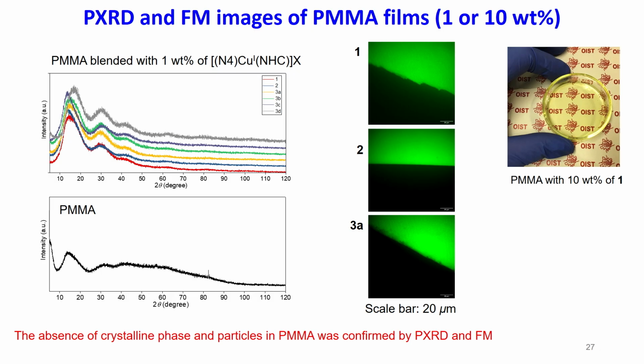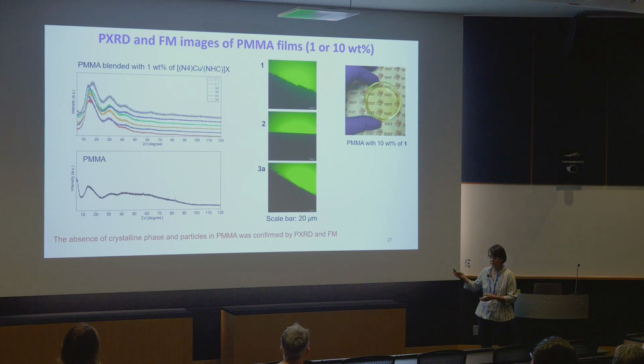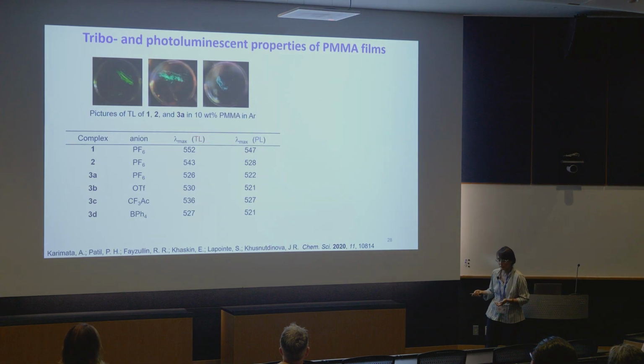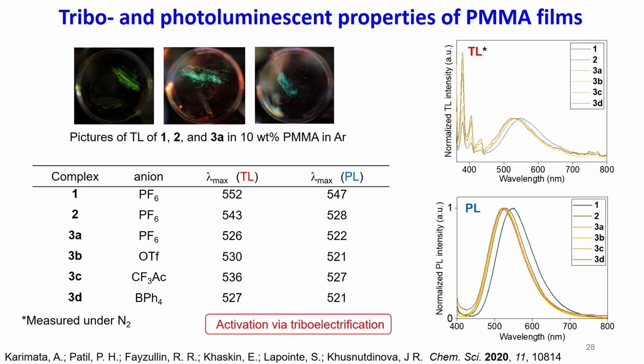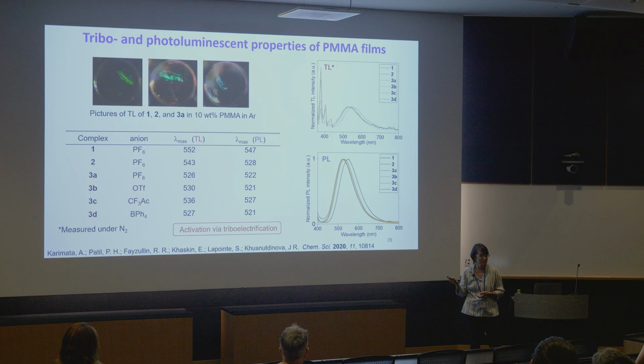Again, we confirmed that the films were actually amorphous. We don't have any evidence of the microcrystalline phase present here. And almost all of our complexes showed triboluminescence in the polymer films. This is how the photoluminescence of the copper complexes in the films looks like. So this is how the triboluminescence of the same complexes in the films looks like. What's the difference? Well, this set of lines here, very sharp lines. And if you remember that spectrum of the cracked sugar light emission I showed before, these are essentially the same lines. So this measurement was really performed under nitrogen gas, and they belong to the discharge of the nitrogen.